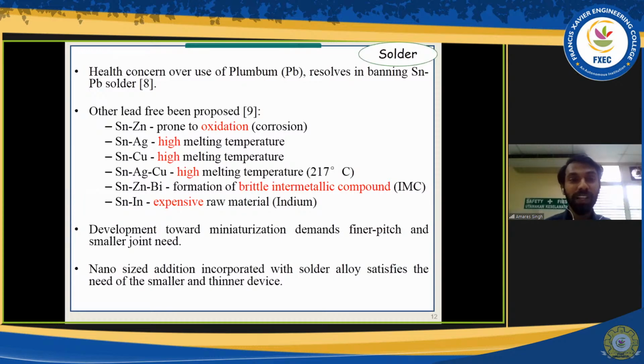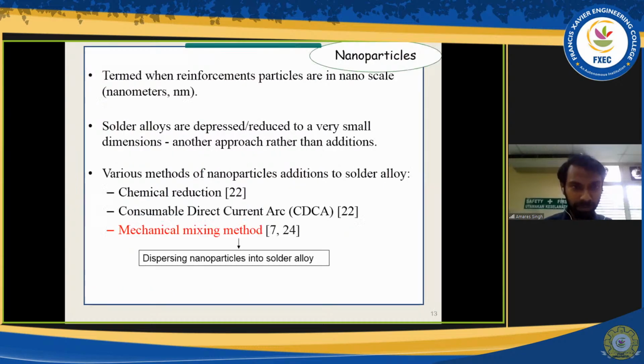At the same time, producing only lead-free solder alone has limitations. So let's say if we want to use a low melting temperature solder, but then we need to increase the mechanical properties, we can't just add another element. So we are looking towards miniaturization, or addition of nanoparticles inside the solder alloy. There are a few methods that have been studied for nanoparticle addition. The first one is chemical reduction. That means they will be using a certain chemical component to reduce or break down the bulk solder to nanoparticles. But this is hazardous and it requires chemists. All right, we are actually engineers, so we try another method, which is the consumable direct current arc method. But this is a very advanced method that needs certain equipment, which is quite expensive.